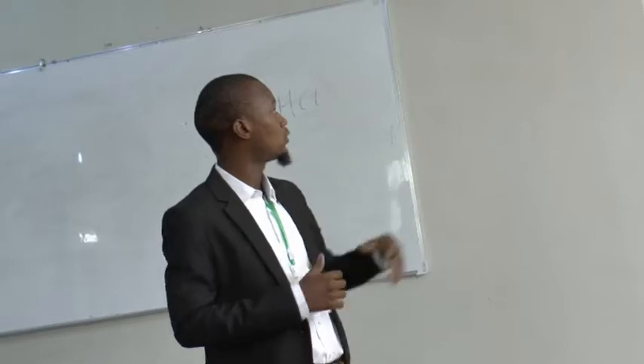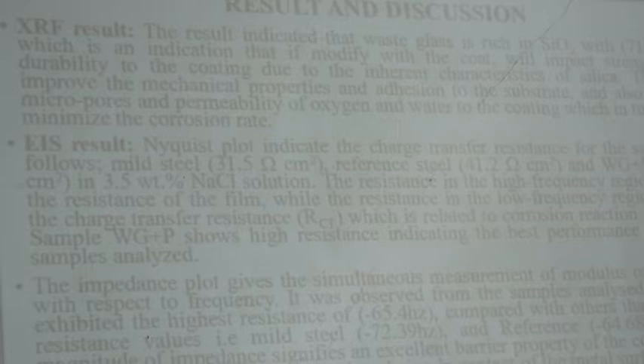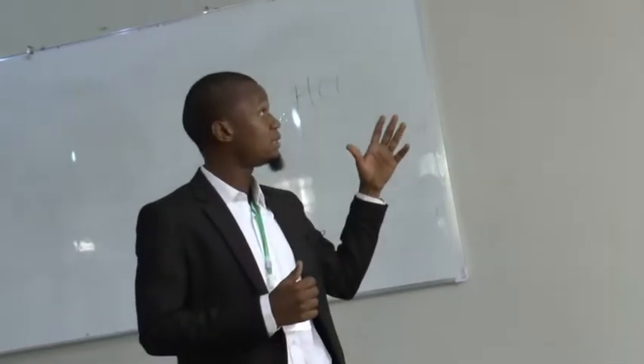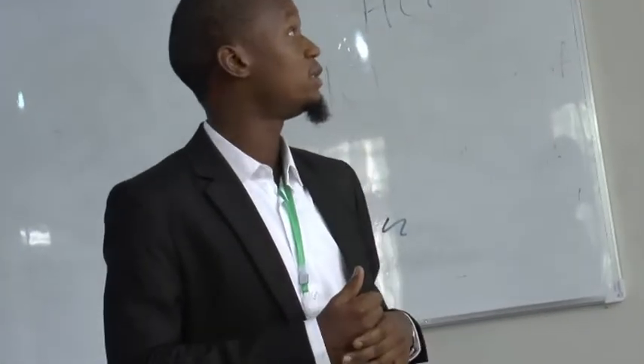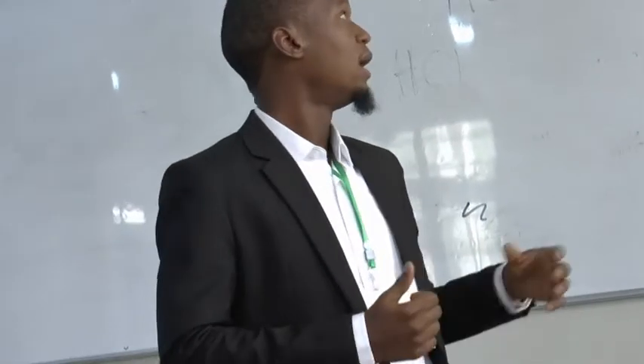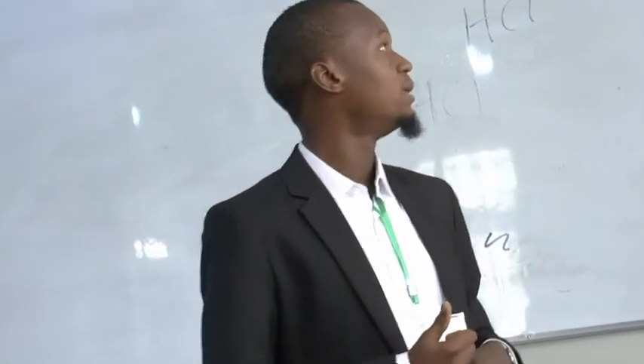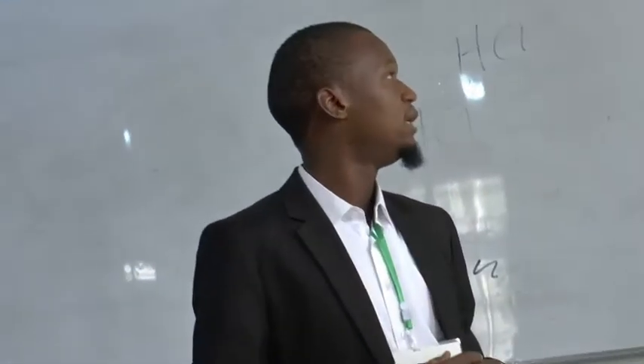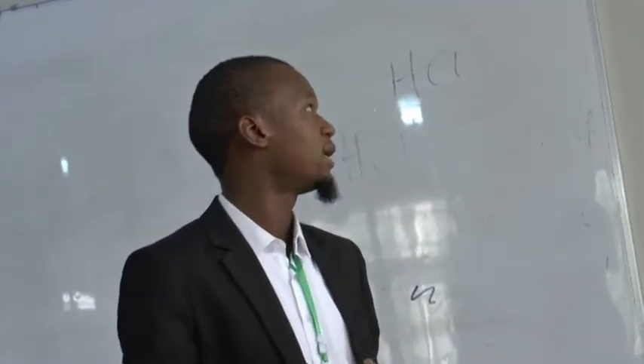Then, the result of the study: the waste glass powder was subjected to XRF analysis, and it was discovered that the sample was rich in silica, of about 71.20%, which is an important indication that due to the inherent nature of the silicon oxide, it can impact durability and improve its mechanical properties.